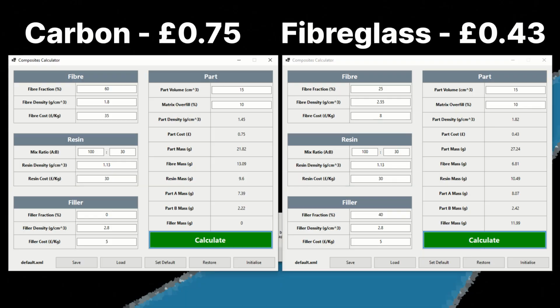Not just the outright cost, but the strength to cost ratio. For this lid, if I did a price comparison, the forged carbon part would end up at 75 pence per part, and the equivalent forged fiberglass one, which is this one, is about 43 pence. So it's just under double the amount for a forged carbon part for the same one. So if you don't need it to be the outright most strength to weight ratio, you can actually get a better strength to cost ratio with forged fiberglass.